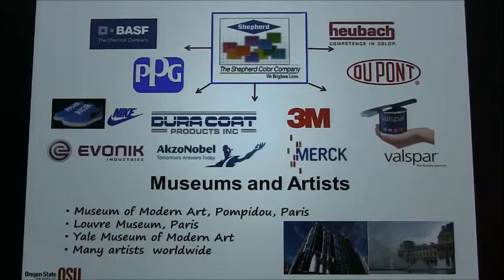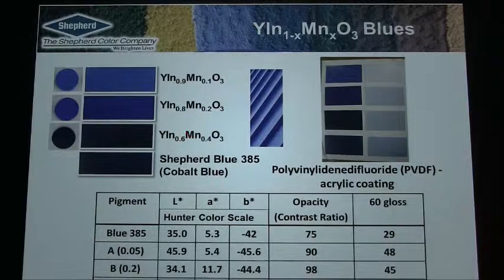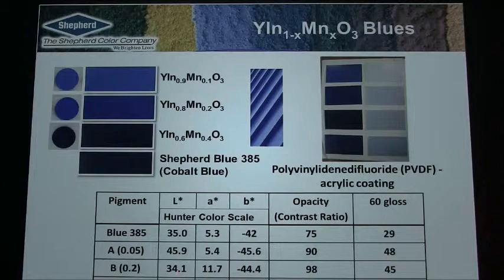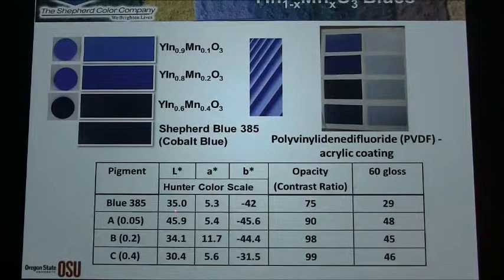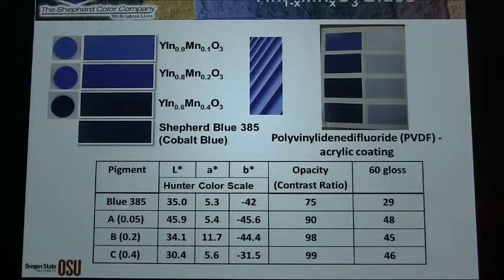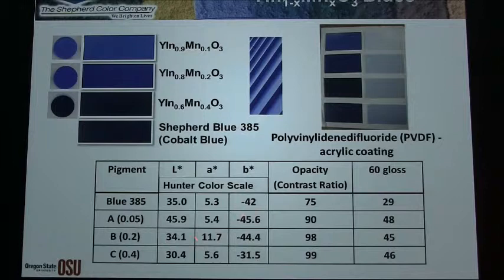This is obtained by the Shepherd Color Company. Shepherd Color Company has developed it into a commercial pigment, and they have evaluated our pigments and compared them with cobalt blue, the blue created by cobalt. Cobalt is a carcinogen, so they have to be very careful. The cobalt doesn't come out of the lattice very easily. So the EPA still allowed them to use cobalt aluminum oxide as a pigment, provided the cobalt won't leach out very easily. So they compare with the cobalt blue, which is used for painting roofs, as well as sidings, for example the vinyl sidings of homes and so on.